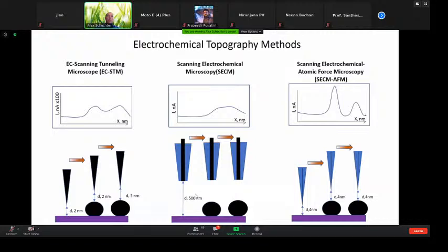The problem with SECM is that we have to keep a large distance from the surface, because it has to be at a constant distance from the surface. Otherwise, we'll run into the same problem as with STM. We need to separate between the current that controls the position, and the current that comes from the reaction. While in AFM, this is now our method, we use the force modulation to position the tip, and we use the inner electrode to control the reaction. So we have 2 measurements at the same time, both position or force topography, so we can get much better resolution, because we can do that at a distance of around 4 nanometers from the surface.